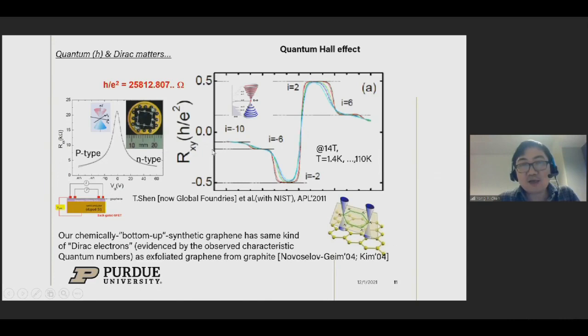The quantum Hall effect, in fact, has been observed in a couple of different materials in various types of 2D electron systems. But in the Dirac electron system like graphene, they have these very interesting quantum numbers, 2, 6, 10, and so on and so forth. And this quantum number series is a signature of these Dirac electrons from the Dirac cone band structure, okay? It was the quantum Hall effect with this quantum series first found in exfoliated graphene, and now this experiment shows these synthetic graphene, even at such a large scale, have this very important characteristic relativistic-like quantum electron property just like exfoliated graphene made from a top-down approach.